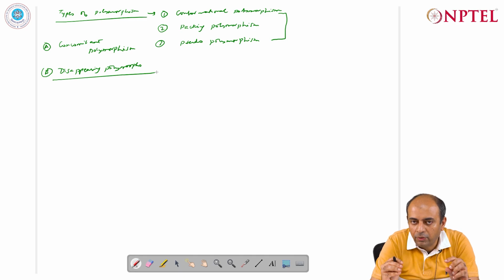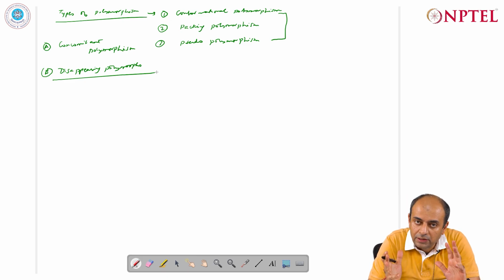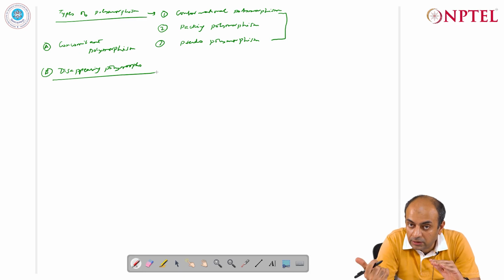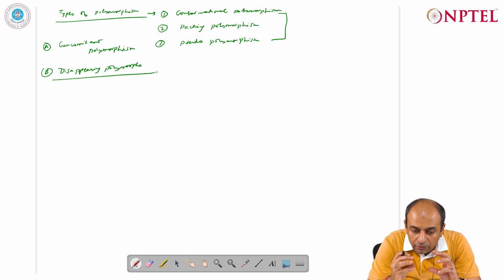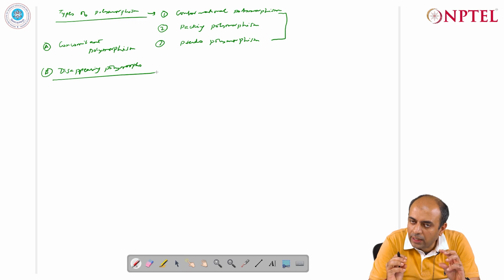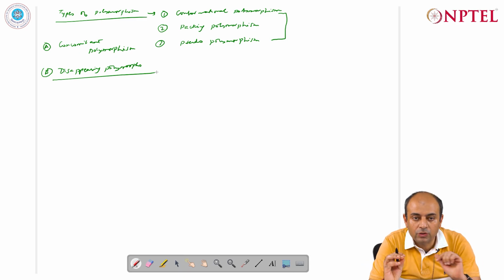Another important property of polymorphs is that the lattice energy is different, and the differences in lattice energy are very small, between 1 to 3 to 4 kcal per mole. So the differences are small. So you can still have, in principle, theoretically, an infinite number of arrangements possible for a given compound. But what you realize experimentally is only a few of these arrangements, which correspond to the Gibbs free energy minima. These correspond primarily to the thermodynamic minima. You can also get the kinetic minima, where kinetic crystallization conditions are satisfied, and you can get kinetic polymorphs. So basically what is happening is that there is an overlap of this crystallization domain, in which two different polymorphs with two different arrangements but having nearly similar lattice energies can crystallize out simultaneously, and that phenomenon is referred to as concomitant polymorphism.